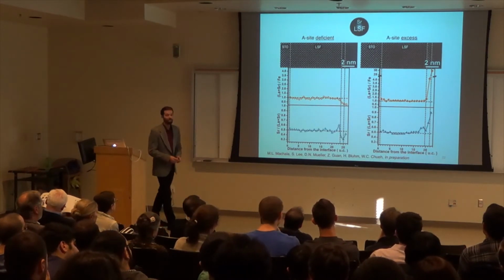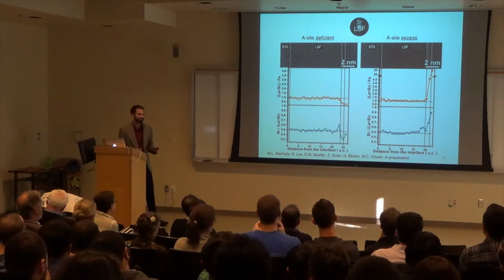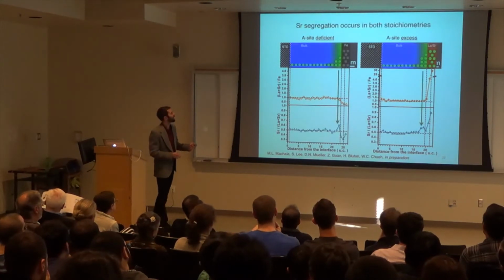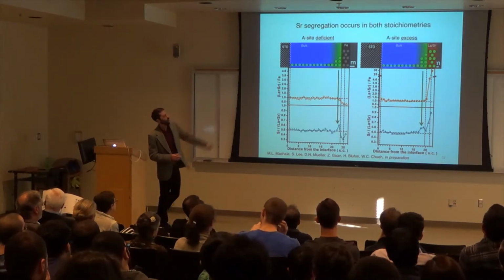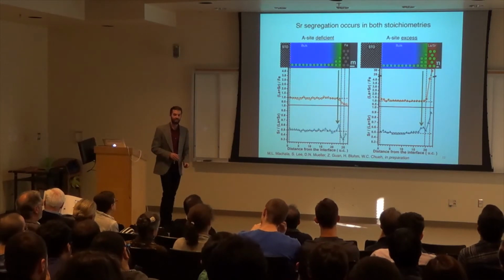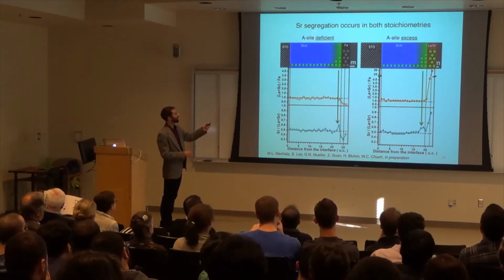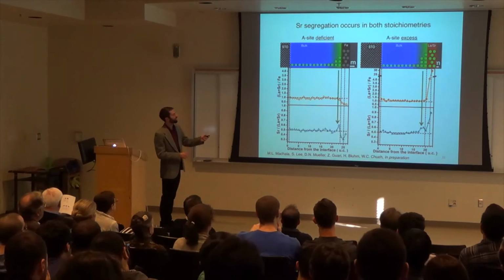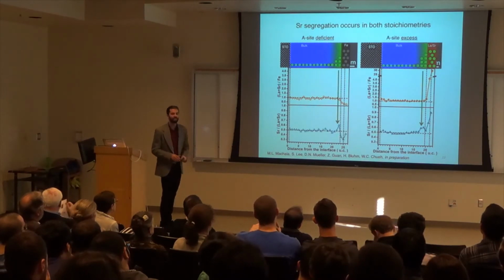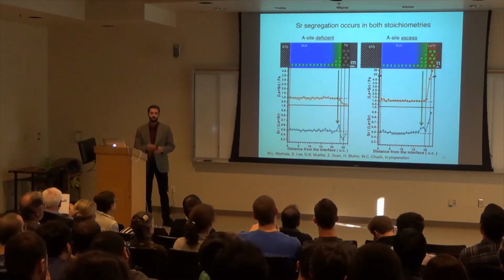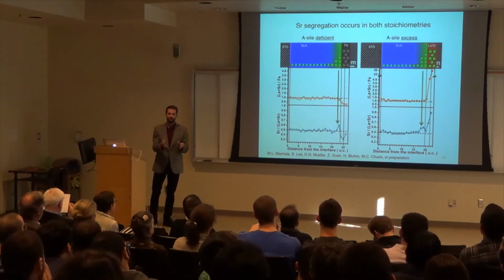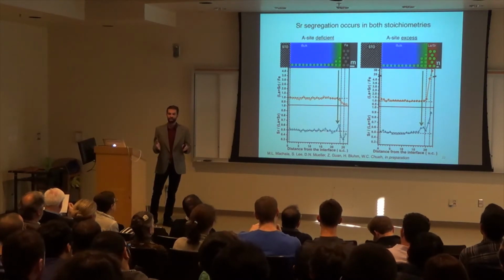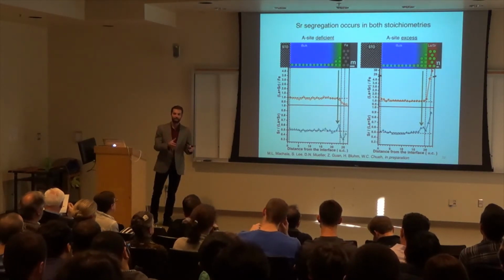Now, to summarize this graph, there's a lot going on: we see a B site termination on the A site deficient layer. And then on the A site excess, we see an A site termination. So for the material that has the same atoms inside of it, we can get 2 different terminations depending on how much of one site we put in versus another.